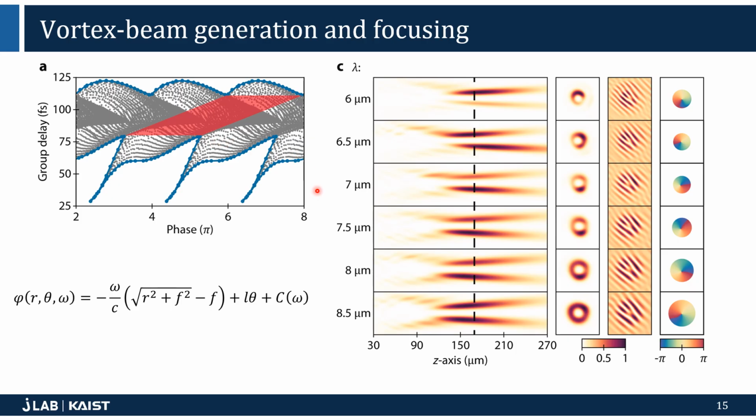Here we show a metalens with a topological charge of -1. Again, we see that chromatic aberrations are significantly reduced. And we see at the focal point, the cross-sectional intensity profile reveals the characteristic donut shape of vortex beams that indicates a singularity in the center. We also combine the electric field components with a linear phase ramp. This is similar to performing an interference experiment in practice. And fork dislocations are observed. These verify the phase singularity.